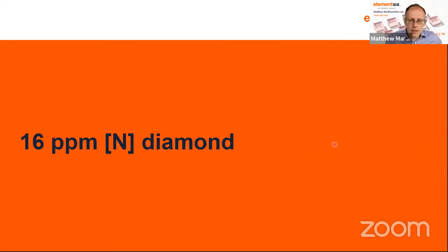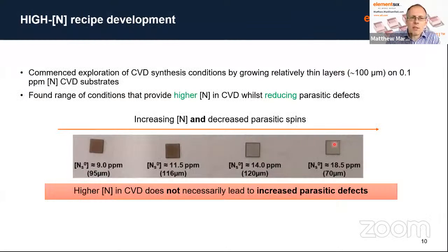Moving on to our first case study in diamond materials, which is the 16 ppm diamond we've been developing. Generally speaking, when you grow diamond via CVD, you're growing material in a regime where diamond isn't the stable phase at room temperature and pressure. Carbon really wants to be graphite, not diamond. So if you don't control the properties right, you can add in a lot of parasitic defects. We did a small study where we grew relatively thin layers, about 100 microns, of high-nitrogen material on low-nitrogen CVD substrates, so that we could do short loop experiments to understand the key parameters affecting the nitrogen and also these parasitic defects.